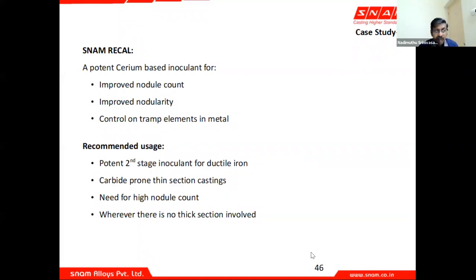So the Recal, the cerium based inoculant, is used for improving nodule count, improved nodularity, and control of tramp elements. A recommended usage is as a potent second stage inoculant, which means the addition rates are 0.05 to 0.1% max. The main reason why we say use it sparingly, where it is required and not in high addition rates, is that cerium and lanthanum, you don't lose them. So as you keep adding your returns, they keep accumulating. So if at one point of time your cerium percentage exceeds the permissible limit, then you have chunky graphite.